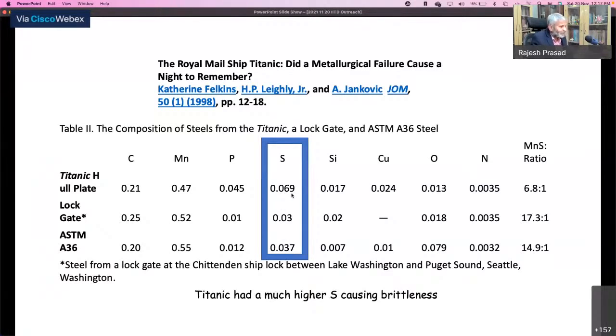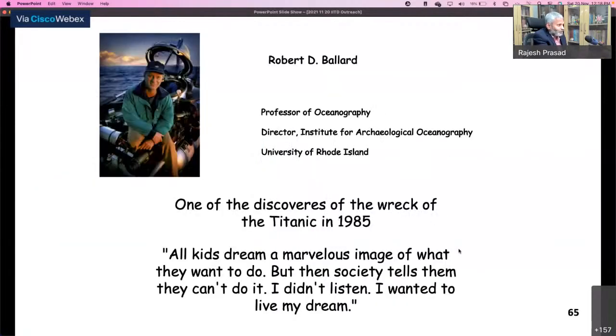It seems very low and you can neglect it. But no, such a small amount also matters. Although small, you can see that it is higher than the value in the modern steel. It was very, very disastrous to have sulfur in steel, which leads to brittleness. So this is one of the Titanic material plates, and the low temperature in which it was operating both contributed to the brittleness of the hull plate, causing that failure which we are all familiar with.